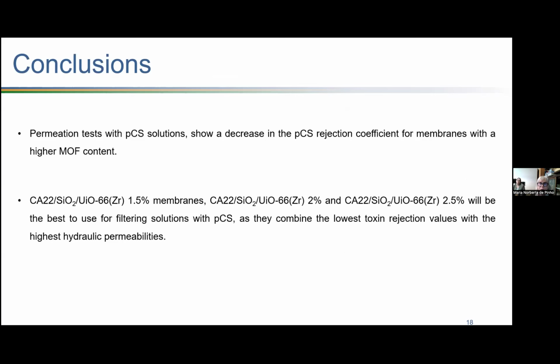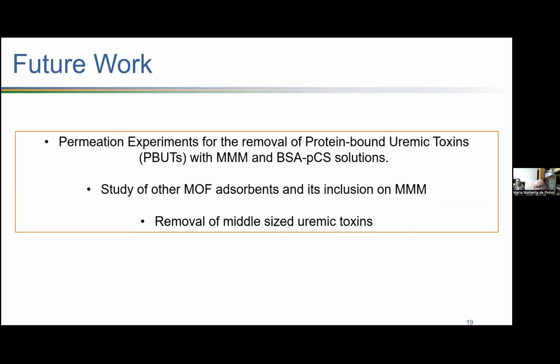Okay, and so there is a decrease in the rejection coefficient for membranes with higher MOF content, and we think that the membranes with 1.5%, 2% and 2.5% will be the best ones for the filtration or the competition with the albumin for the removal of the p-cresyl, as they combine lowest toxin rejection with high hydraulic permeabilities and high fluxes of the permeation.